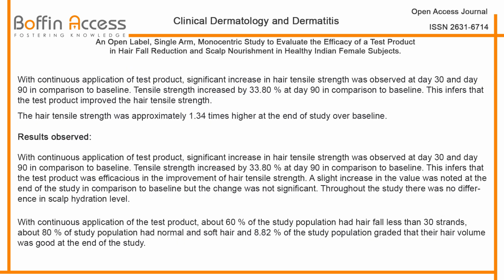With continuous application of test product, significant increase in hair tensile strength was observed at day 30 and day 90 in comparison to baseline. Tensile strength increased by 33.80% at day 90 in comparison to baseline. This infers that the test product improved the hair tensile strength. The hair tensile strength was approximately 1.34 times higher at the end of study over baseline.